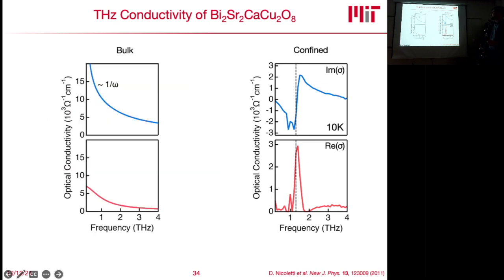And if we compare this now to the bulk response of a superconductor, BSCCO, where these numbers and trends are based on real data, you get a very different response. In BSCCO, you would expect a 1/omega divergence in the imaginary part of the conductivity. What we get is a derivative line shape at finite frequency. In the real part, you would expect some residual scattering due to uncondensed carriers, which should also happen at low frequencies. We again get a finite frequency peak. So it's already very different to the light-matter coupling in a macroscopic sample.